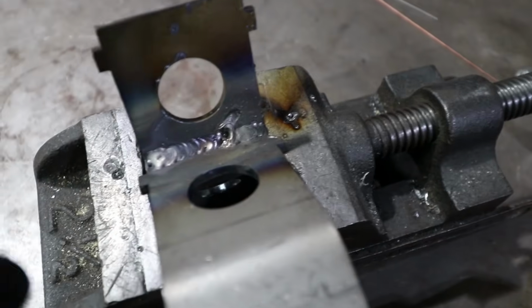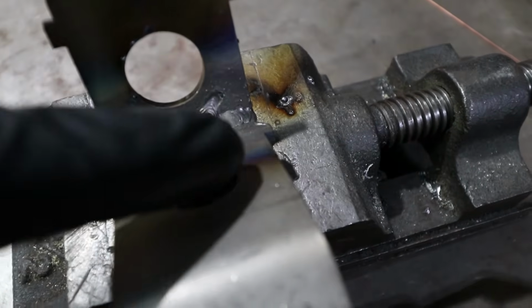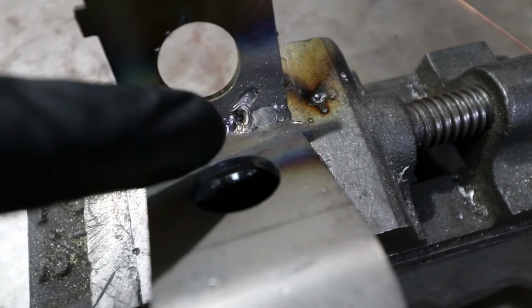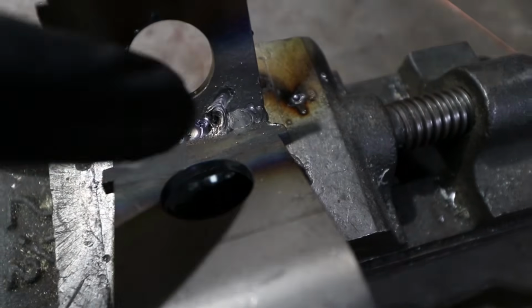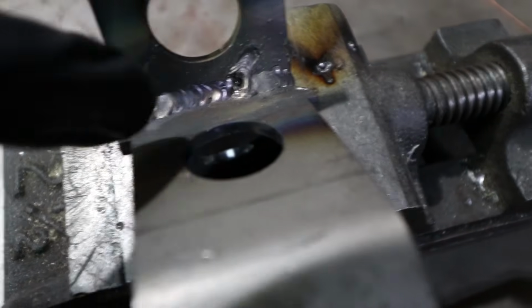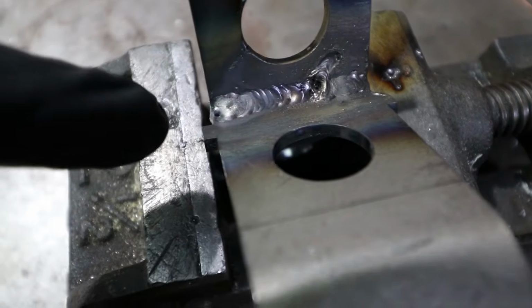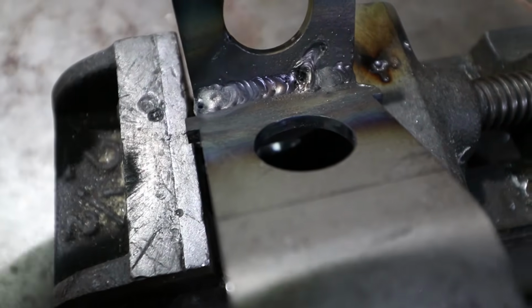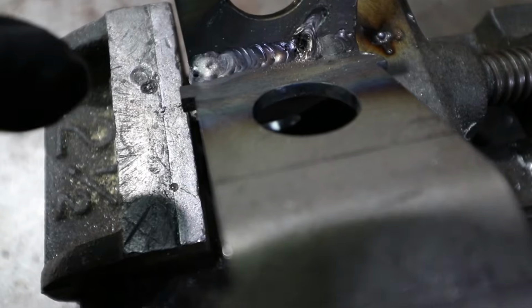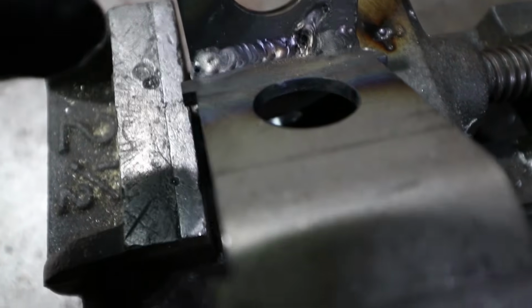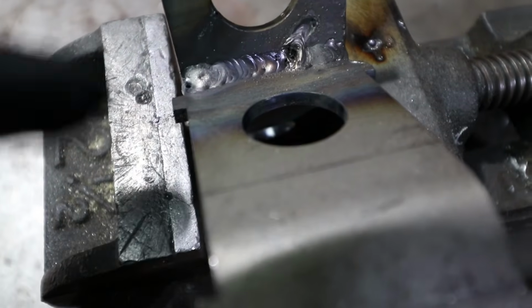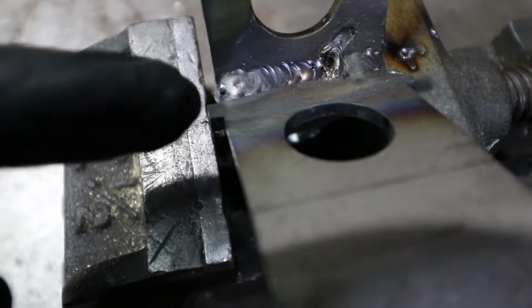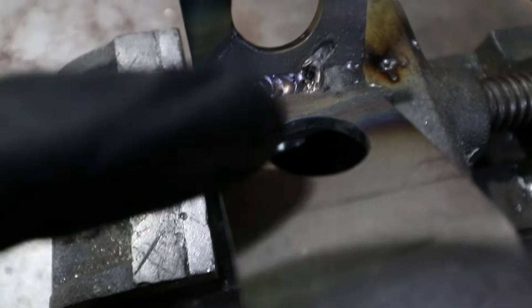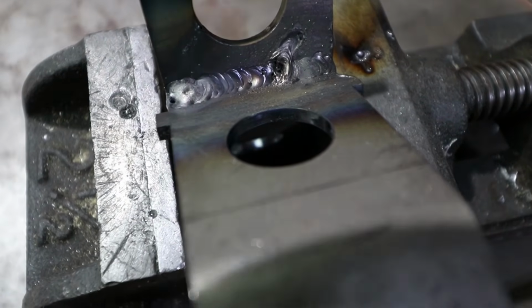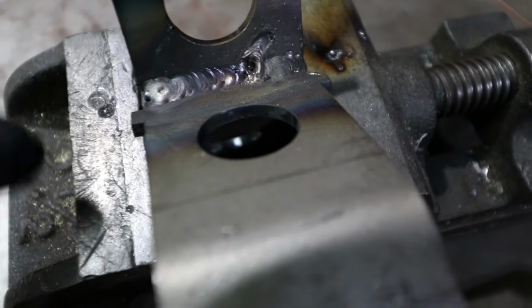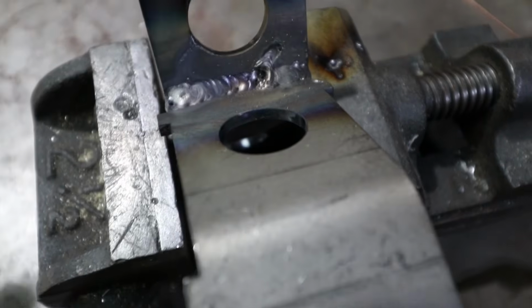Okay, this was not rehearsed, and I definitely made some mistakes on this. Got started, the filler wasn't the right size. I forgot to turn the gas on, so you can see the huge porosity there and the mistake I made. And then right here was welding pretty well. And then right here at the end, I could see it burning through. Normally I would let off the pedal because you do a little bit fewer amps on the end, but I might have had the amp set too high, because I had to just add more filler to prevent this from just getting eroded away. So overall, I'm just kind of showing you the machine will definitely do it. If I was doing this for myself, I would have done some practice pieces and gotten the machine dialed in a little bit better, but it absolutely will work.